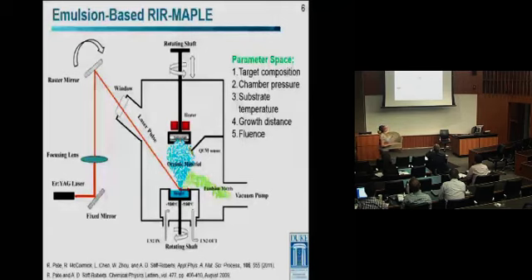So we have active cooling by liquid nitrogen during the deposition process, and this gives us the solid target. The basic idea then is that the laser energy is absorbed by your matrix material. So that's the matrix-assisted part. That matrix material evaporates, and you have the gentle transfer of whatever your target material is, which is typically organic, let's just say a polymer chain, gently transferred from the target to the substrate. And we have various parameters that we can control during this vacuum deposition process.